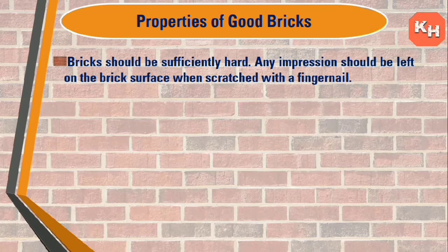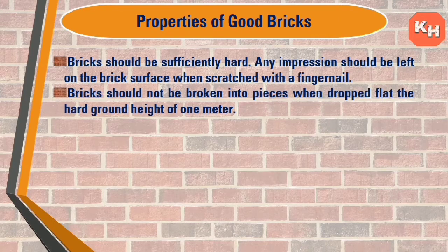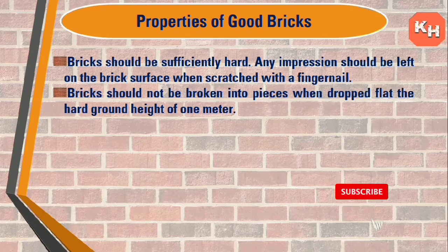Bricks should be sufficiently hard — no impression should be left on the brick surface when scratched with a fingernail. Bricks should not break when dropped flat on hard ground from a height of one meter.